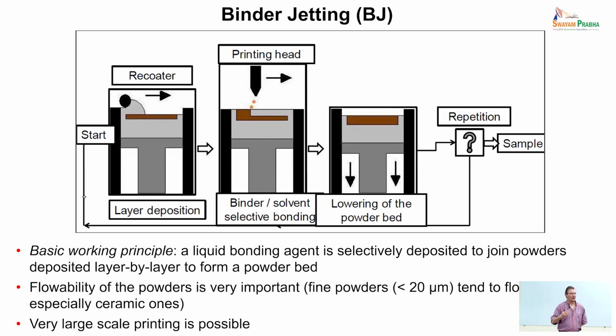One issue that you have with this technology, this also would apply to selective laser melting and sintering, is that in order to generate your powder layer, you need what is called a flowable powder. For instance, if you take flour and you want to spread a layer of flour, which is simply very fine organic particles, you will see that it is difficult to achieve a thin, defectless layer of flour, because you have interaction between the particles, chemical interaction, secondary bonding between the particles, and this leads to the formation of a defected layer with cracks and inhomogeneities.